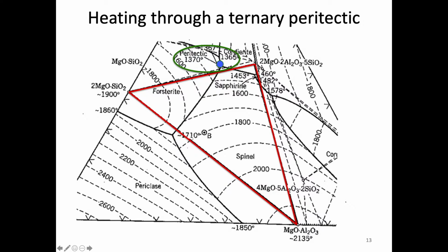phases is actually here. And it's labeled as a peritectic, but we know that it's a peritectic because it's outside of its own compatibility triangle, right? Remember when we talked about that. So this is outside of its own compatibility triangle, and therefore that puts it as a peritectic reaction. So we know we have a peritectic reaction, and the fact that this invariant point is outside of that tells us this. All right, so we've just verified that this is a peritectic.